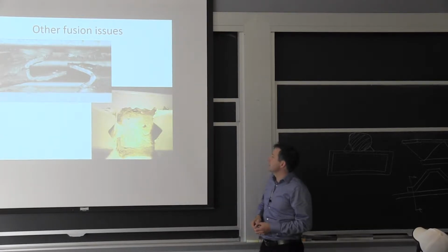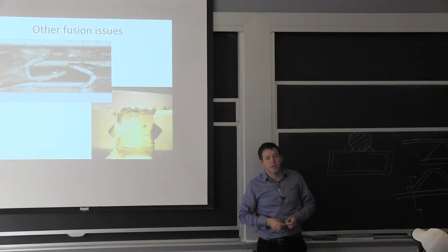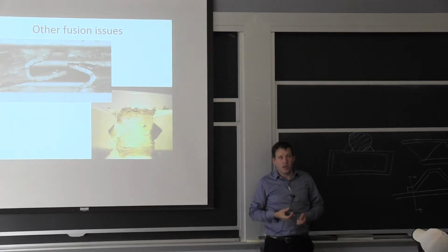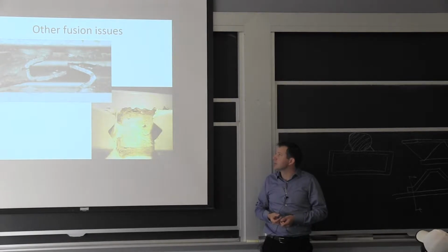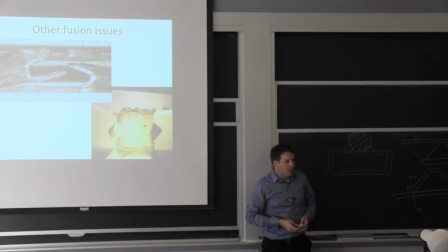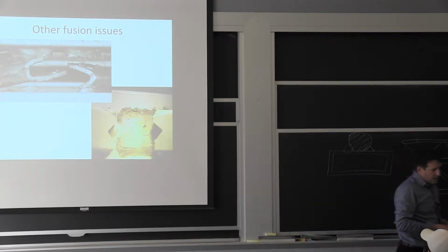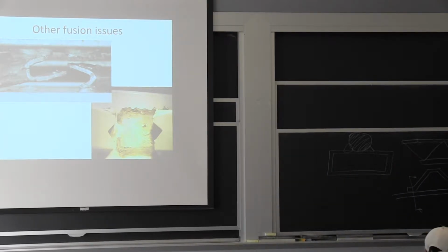So if we look at this joint, we could say maybe 5% of it was fused, which is very little. It creates a situation where you have a pre-crack, and it's easy to fail. Now, one thing that I mentioned is it's not unusual not to control too well the quality of these joints, because the demand on them is not super high.